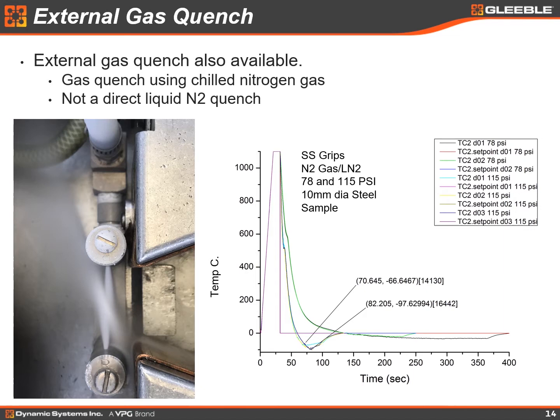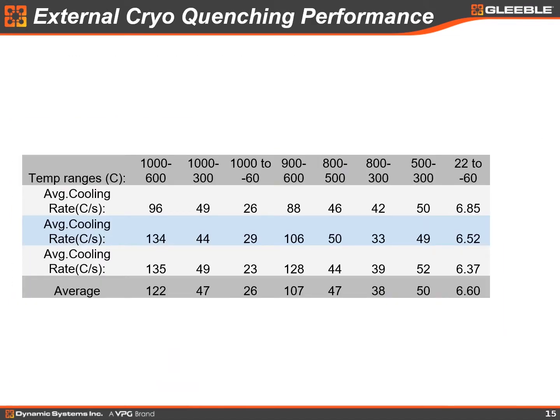The external cryo quenching performance, this is done on I believe a 10 millimeter sample, and just shows the cooling rates from different temperature ranges. So again, fairly fast cooling rates at the higher temperatures, and then once we get down to room temperature to minus 60 degrees or so, fairly slower cooling rates of about 6 degrees per second.